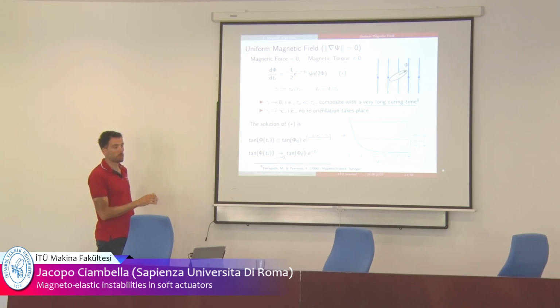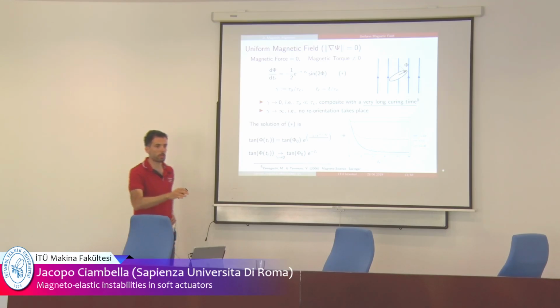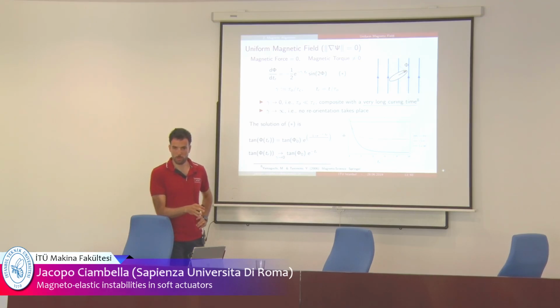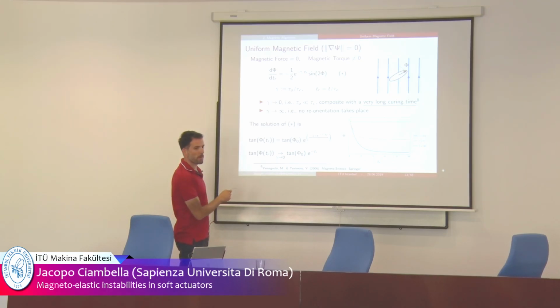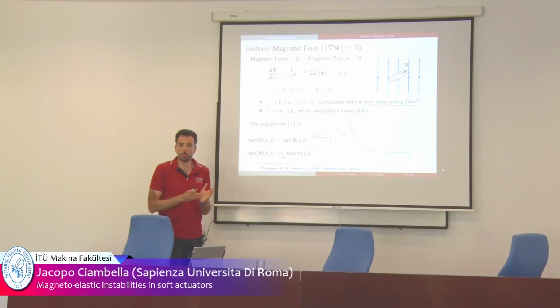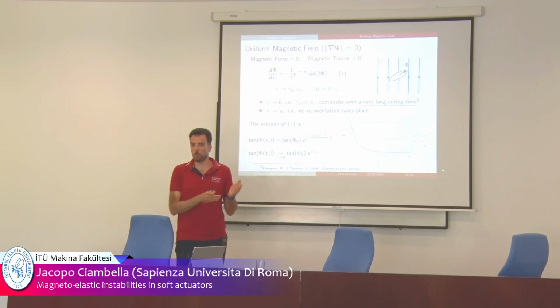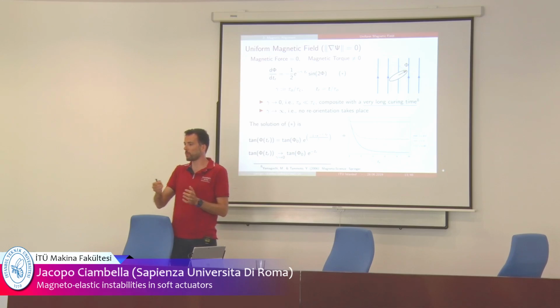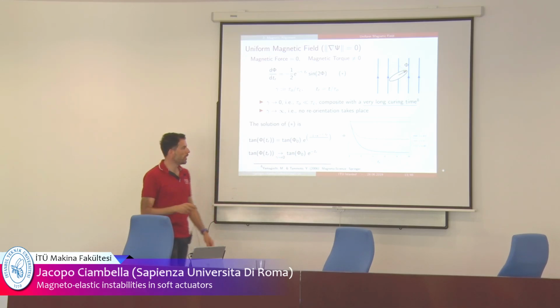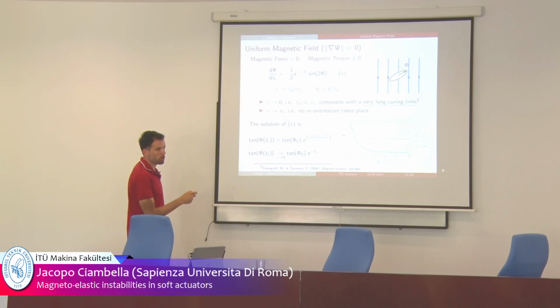Very simple equation. So what happens when gamma goes to 0? It means that the curing time is much longer than the orientation time. On the opposite, when gamma is very big, it means that this composite cures very fast. So, as I will show you, as expected, the particles won't have time to orient themselves. You can work out the solution. It's an ordinary differential equation, linear, so very easy. You can work out the solution in closed form.